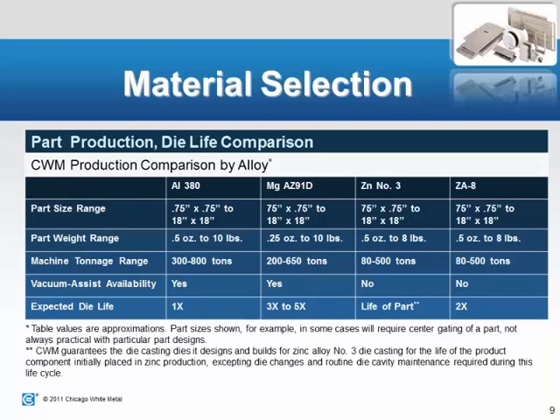Magnesium. The magnesium alloy we have highlighted here is AZ91D. There are other alloys that are available, but this again is the alloy that Chicago White Metal uses. It is the lightest weight of all the die casting alloys. Magnesium is. It's about 2/3 the weight of aluminum, so it's about 1/3 lighter than aluminum.